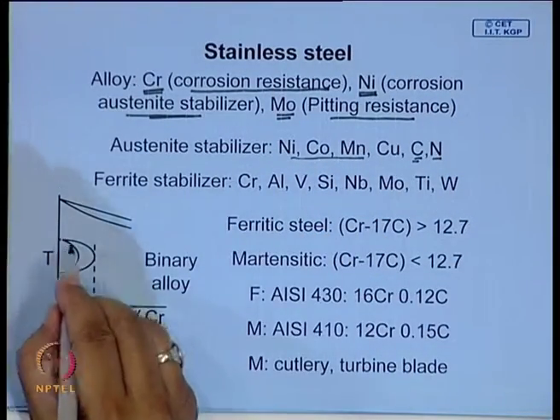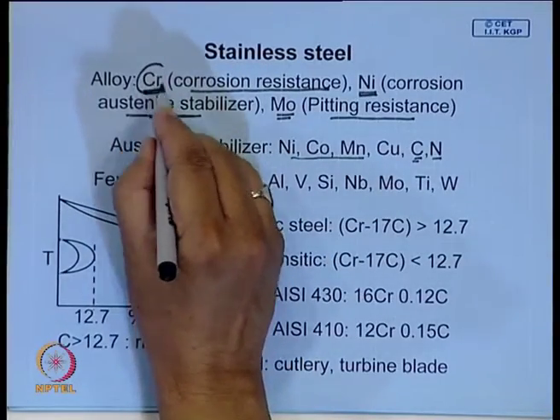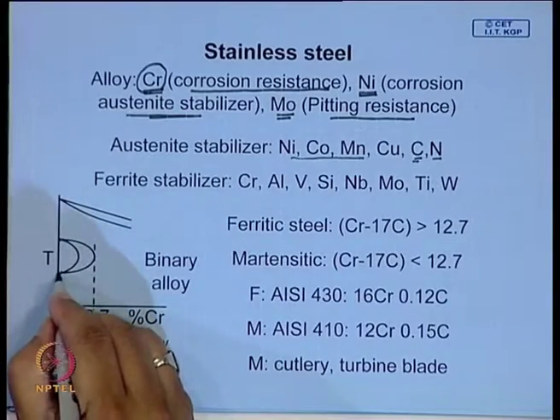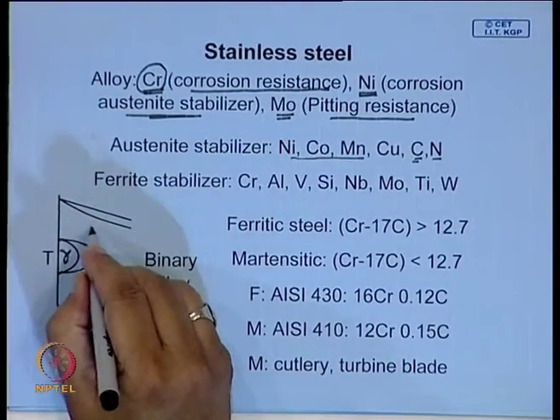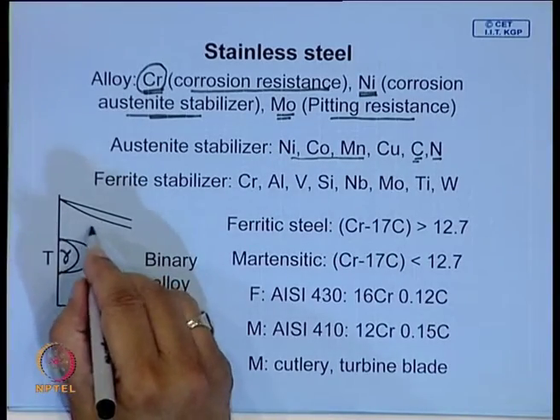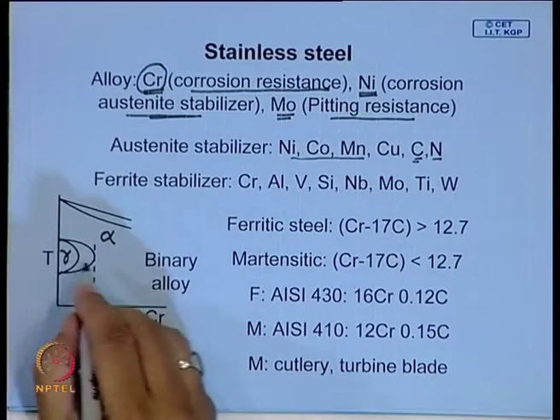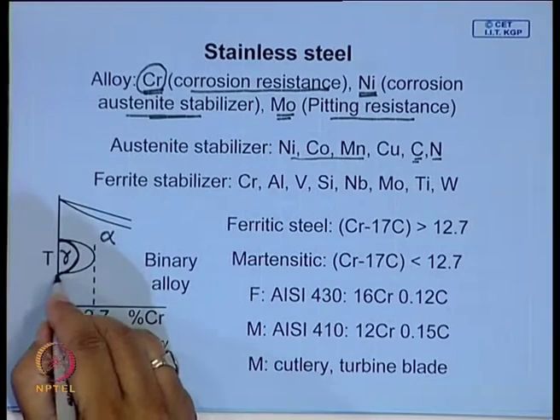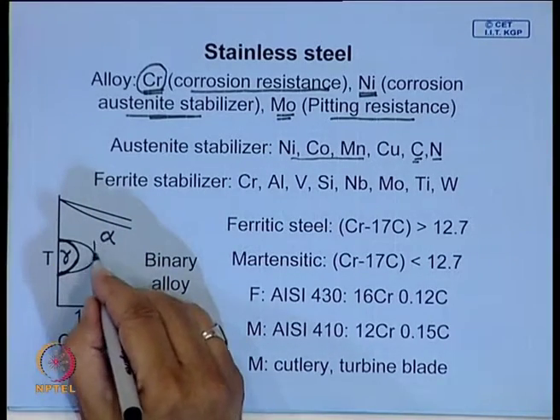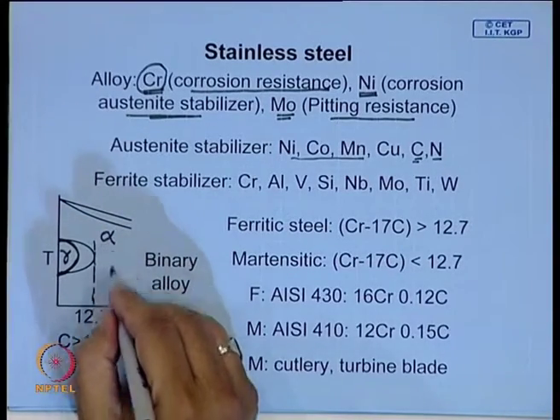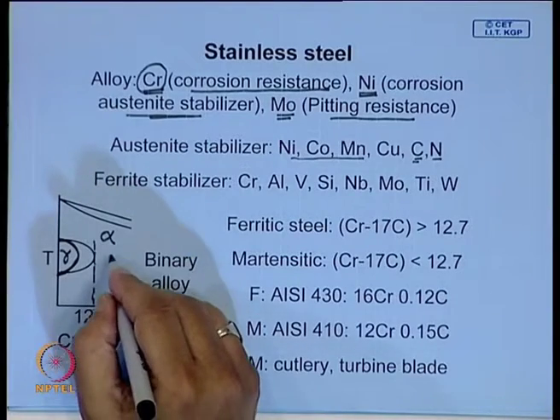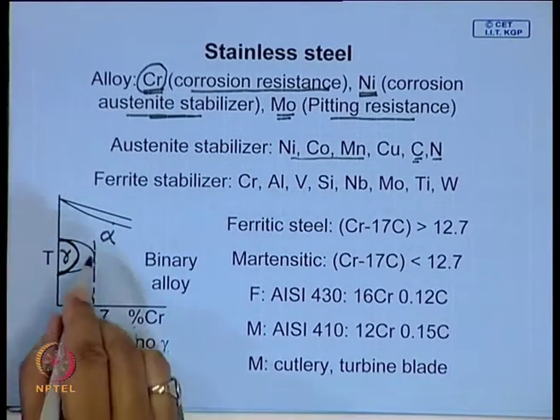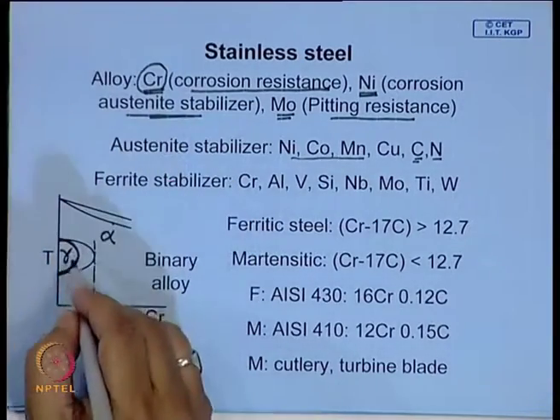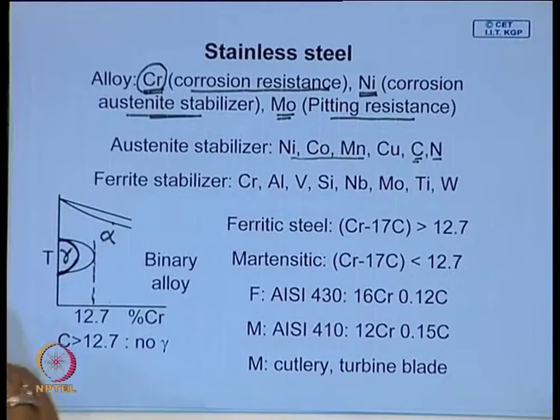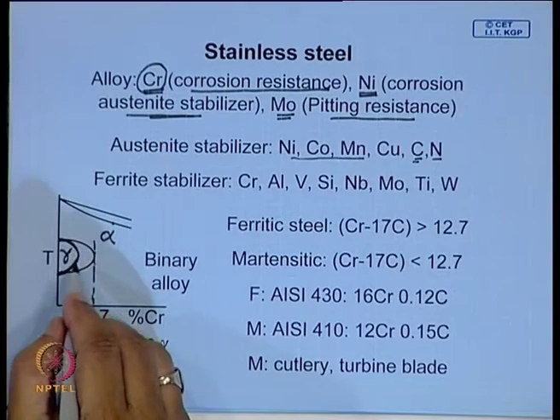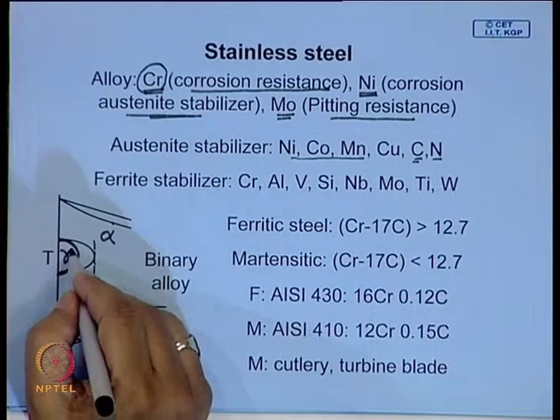Now, a quick look at this iron chromium binary diagram. Chromium is known as a gamma loop forming element. So, here you have ferrite, sometimes we call it alpha or delta, does not matter. So, this side is ferritic. If the amount of chromium goes beyond a critical limit, in that case if you heat the iron chromium alloy, it remains ferritic until it melts. So, you cannot form austenite. If you have too much chromium, then the steel cannot be hardened, or made martensitic by quenching. The question of getting martensite does not arise, because you are not able to reach this austenitic state.